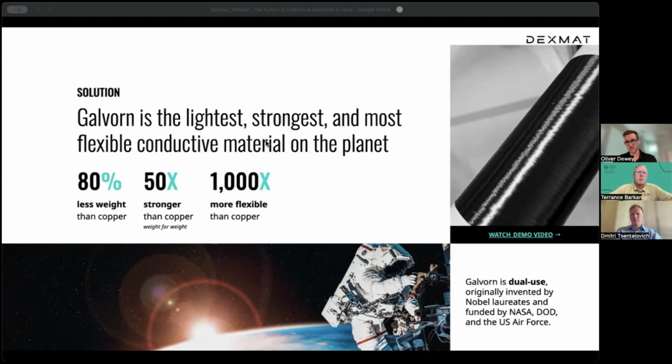Yeah, you're okay if I take this one again, Dimitri? So again, the studies that were done at Rice University demonstrated that if you take carbon nanotube fibers and redissolve them and respin them, you get fibers with the exact same properties as you had after the initial spinning. And if you take fibers produced from high aspect ratio carbon nanotubes and fibers produced from lower, but still pretty high, aspect ratio carbon nanotubes, and dissolve them together and produce a new fiber, you'll get fiber with properties in between the two initial fiber properties.